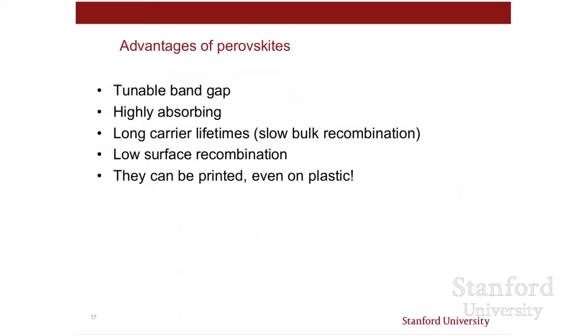A lot of semiconductors have defects at their surfaces, and charge carriers will recombine there, but that is very slow in the perovskite. For a lot of semiconductors, if you have a thin film with lots of small crystals, there will be recombination at the boundaries between crystals, but that seems to be very slow with perovskites. And it's all of those properties that make it possible to get as high as 22% efficiency. And moreover, we can print these things even on plastic, and so we can make a flexible solar cell at low temperature. And that's the property that cadmium telluride and CIGS don't have.